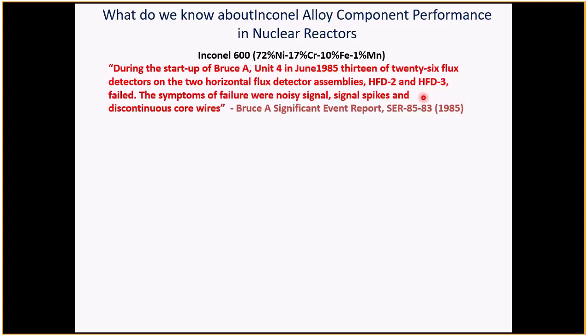These things, when the reactor starts up, the whole reactor vibrates. These flux detectors, which are critical for the shutdown systems, the safety shutdown systems of the reactor, these things just rattled themselves apart.